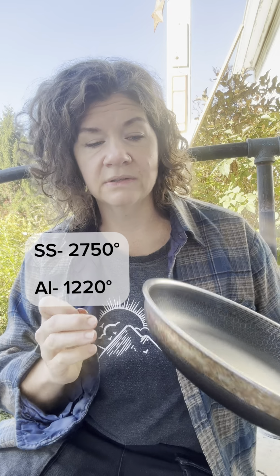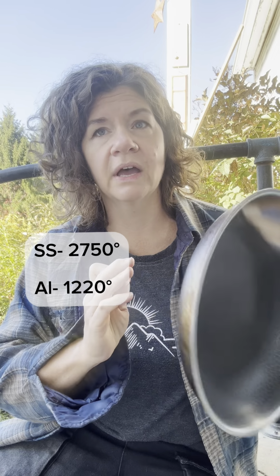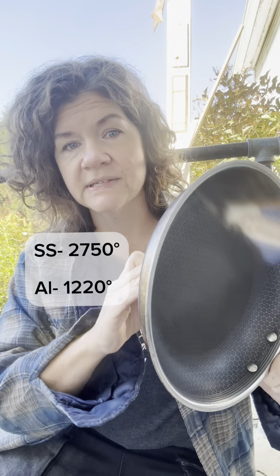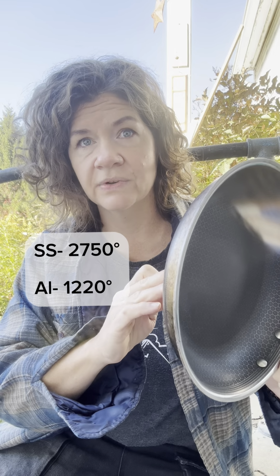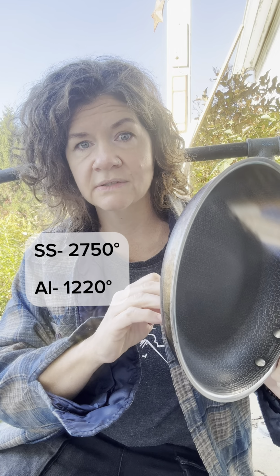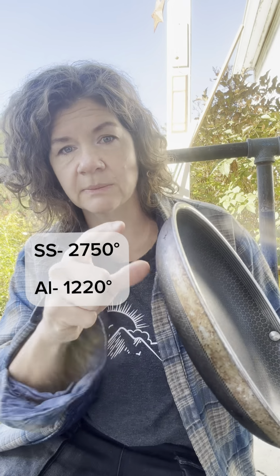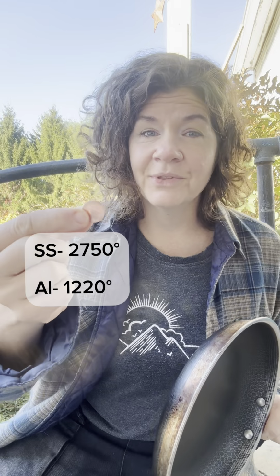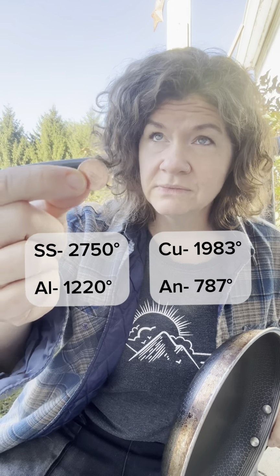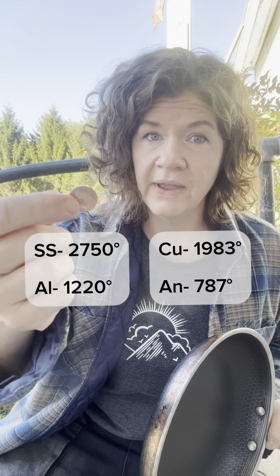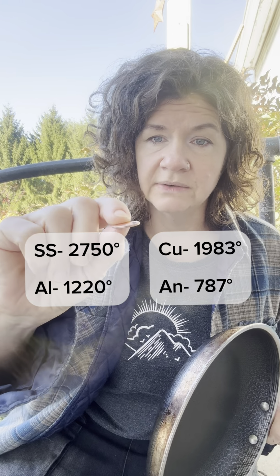By the numbers, the stainless steel on the outside of this pan melts at about 2500 to 2800 degrees Fahrenheit, while the aluminum inside of it melts at about 1200 Fahrenheit. That's a difference of about 1400 degrees. 1400 degree difference between the melting points in the two layers in here. Same with a penny. Pure copper melts at about 2000 degrees, and zinc melts at about 800 degrees, leaving a difference of about 1200 degrees.